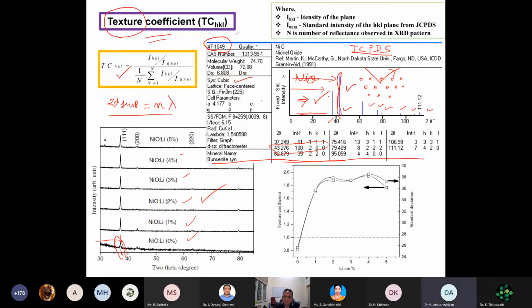This is the second higher intensity peak, then this is the third one, but the intensities are not matching. You see here in my pattern for thin films, the first peak at 37.2 degrees is higher, whereas the actual 100 intensity peak is lesser. This doesn't mean that the compound has not formed on my substrate. That's why thin film diffraction patterns are sometimes a little bit tricky.